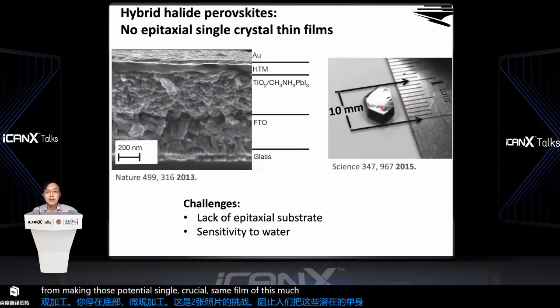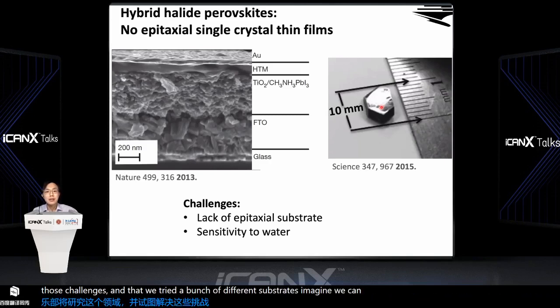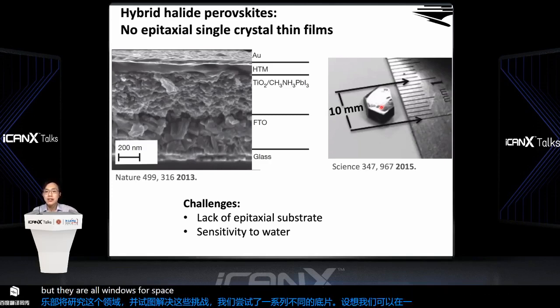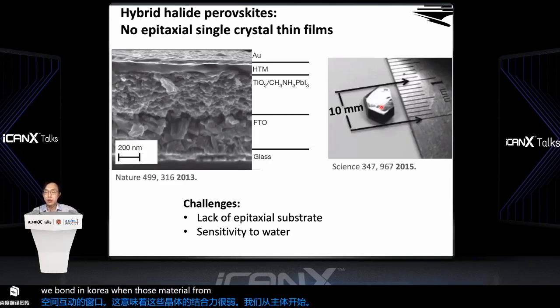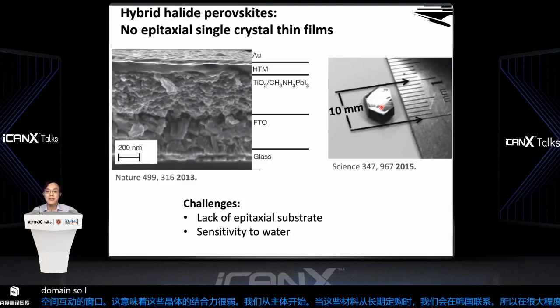So my group looked into this area and tried to tackle those challenges, and we tried a bunch of different substrates. Eventually, we can grow some materials on some substrates, but they are all van der Waals force-based interactions. That means those crystals have a very weak bonding with the substrate, and that weak bonding prevents those materials from long-range order. So on a large scale, they are polycrystal, but they have those large domains, right? So they are still not perfect.